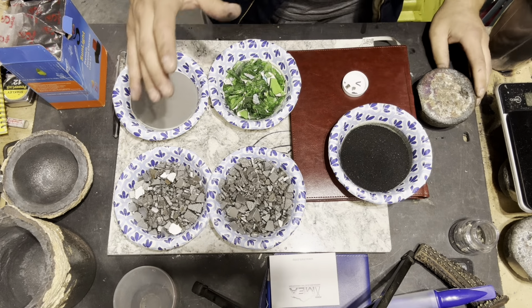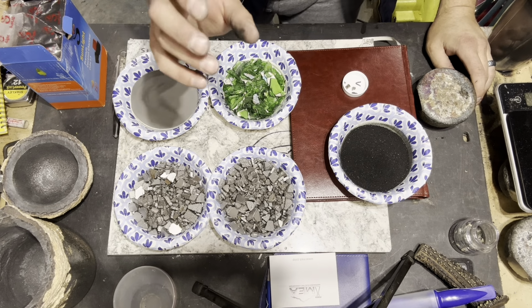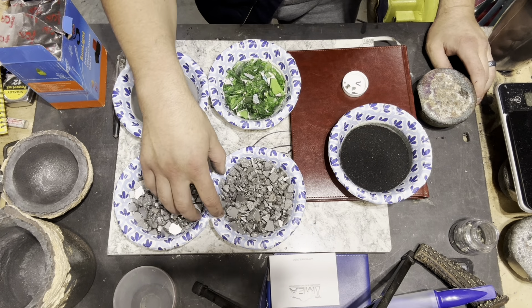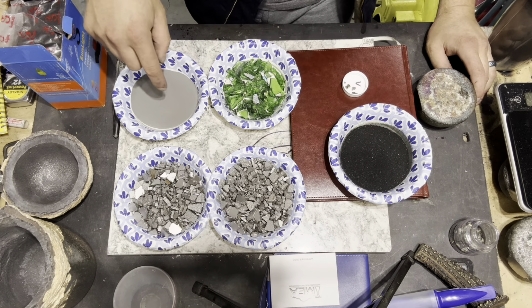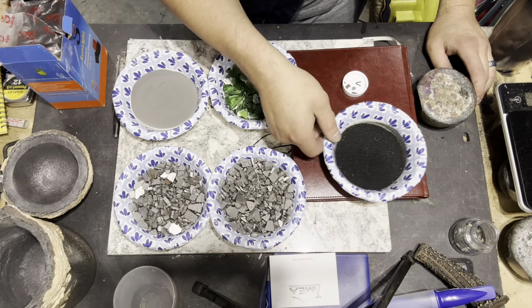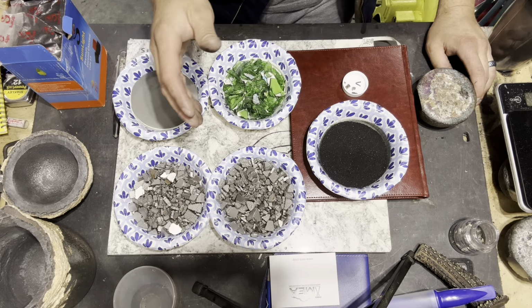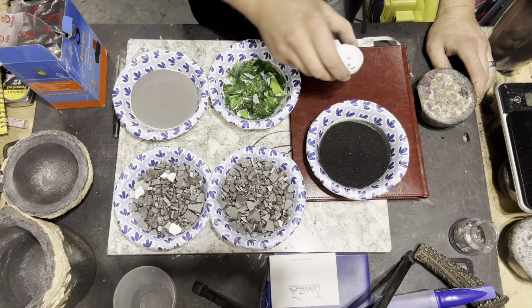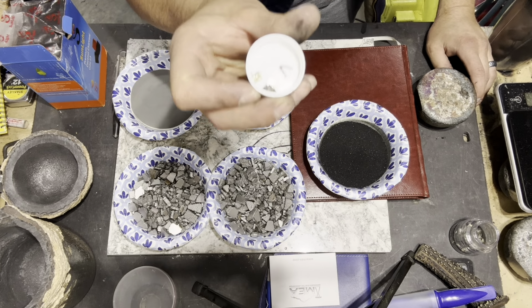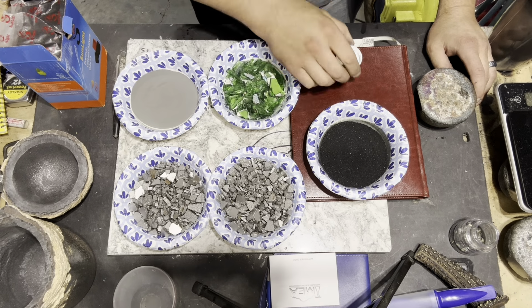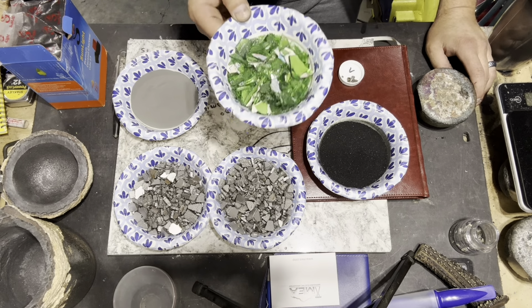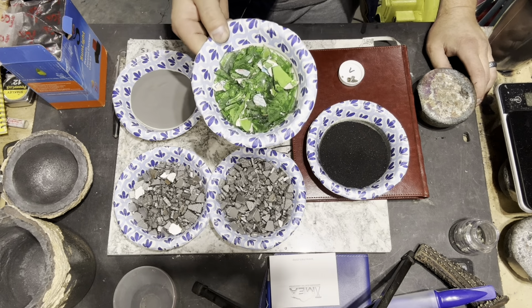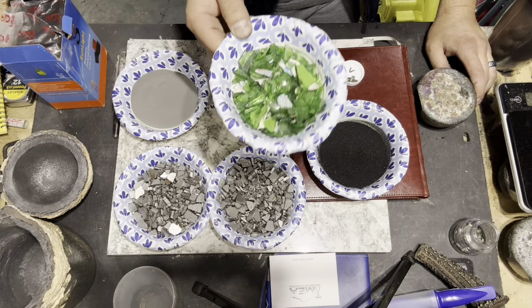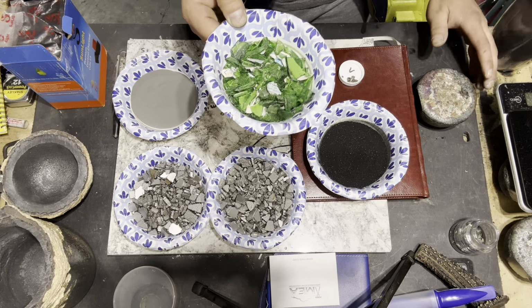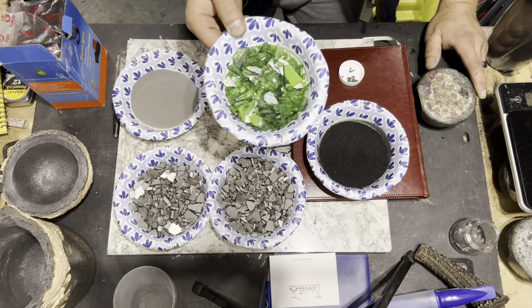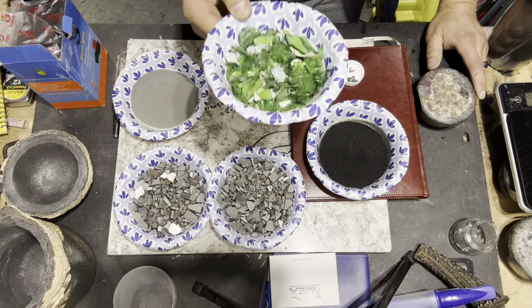I have everything measured out. This is going to be a 2,400 gram ingot. So I've got 2,050 grams of iron flake, 300 grams of iron phosphorus powder, and 50 grams of charcoal. So that'll make a 2,400 gram ingot, plus the 1.8 grams of ferrovanadium. Now, one thing I do, and something I've been doing recently, and probably the last 15 melts, is I actually weigh my glass. I use the exact same amount of glass every time. So roughly about 200 grams, plus or minus isn't gonna hurt anything, but don't want too much green glass.